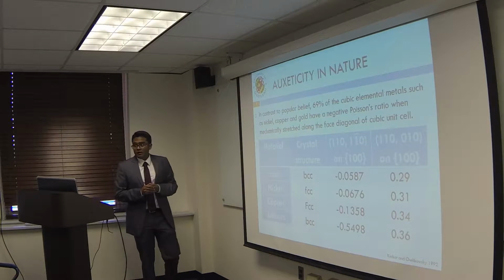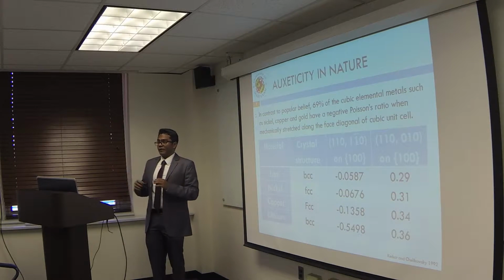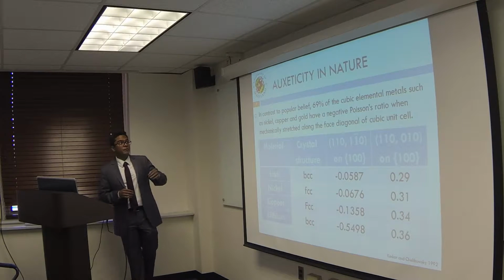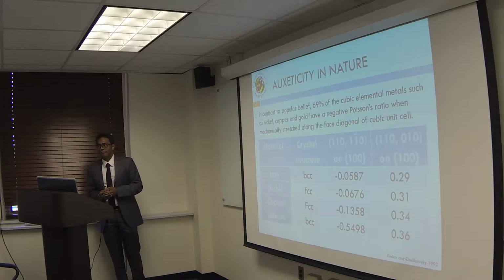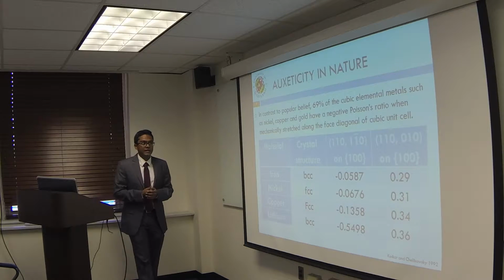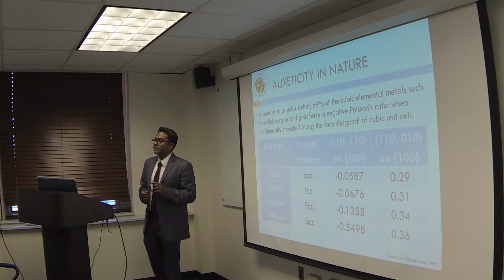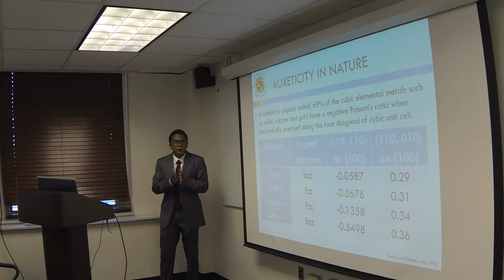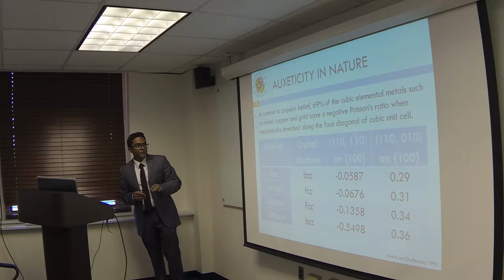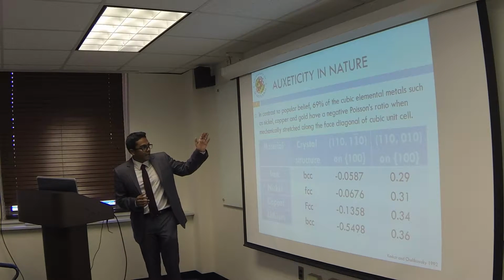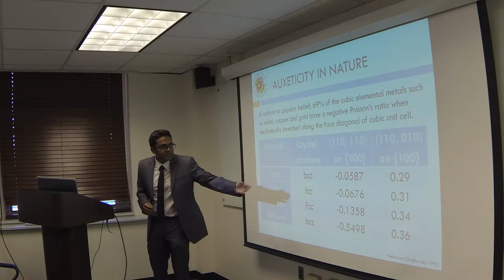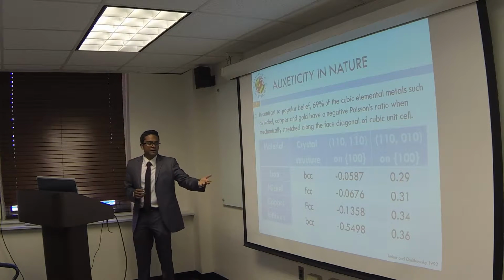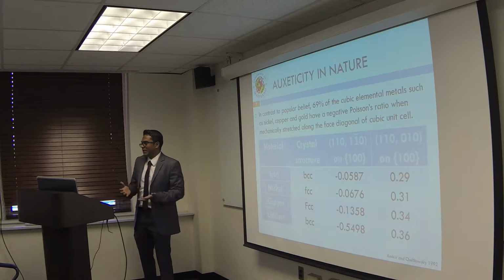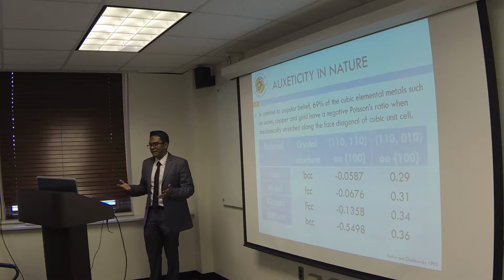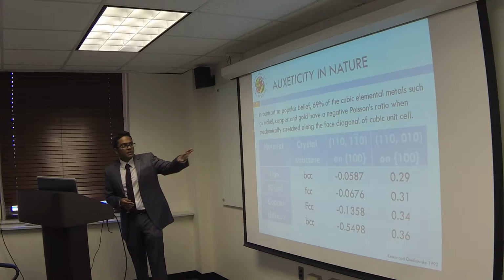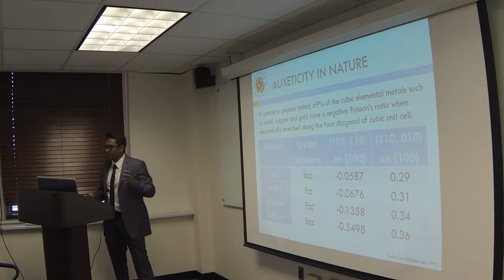Humans have known about auxetic materials for a number of years now. And contrary to popular belief, more than 69% of cubic metals are known to exhibit a negative Poisson's ratio. But what's interesting is that this effect is shown only in a particular crystallographic direction, which is the 110 direction. And if you look at the chart here, you can see that the values of negative Poisson's ratio are really, really small, except in the case of lithium, of course. But lithium has a really low strength modulus, and you can't really build any applications out of lithium. So let's discuss what the 110 direction actually means.